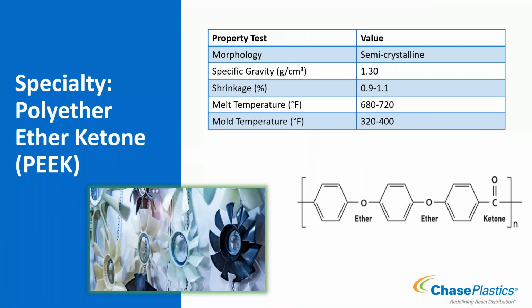So now we're talking about additional specialties. We're talking about PEEK, so polyether ether ketone. Its morphology is going to be semicrystalline, specific gravity of 1.3, a little bit higher shrinkage, about 1%, because it's a semicrystalline material. And now we're getting into some pretty high temperature products. We're in the 700 range for our melt temperature, comparing that all the way back to our commodities that were in the 400. So you can see the big difference in our temperature performance. And then our mold temperatures are also very hot, almost 400 degrees Fahrenheit for polyether ether ketone.